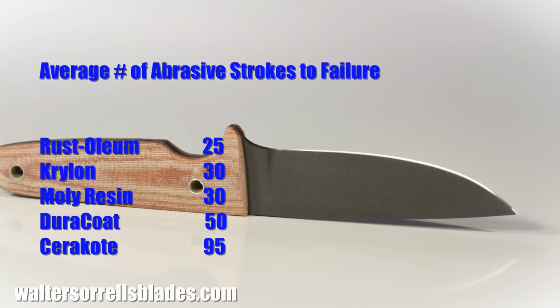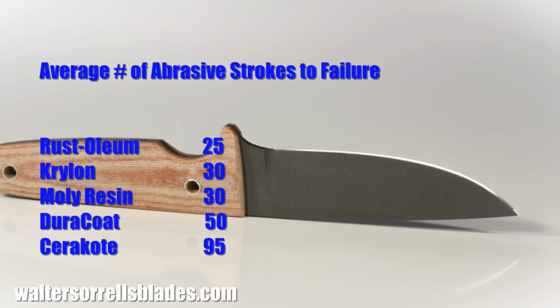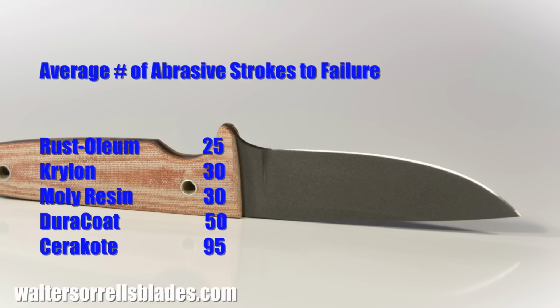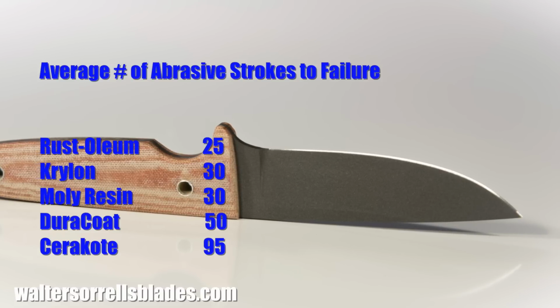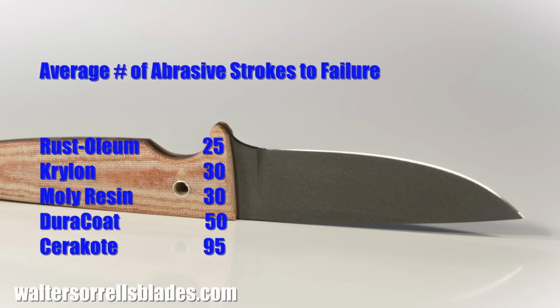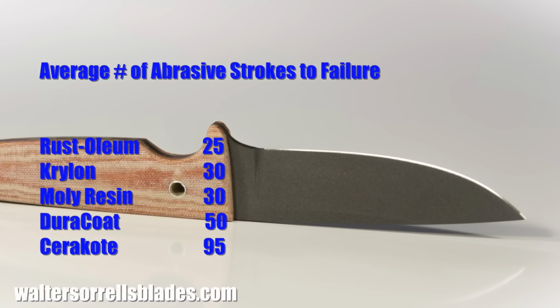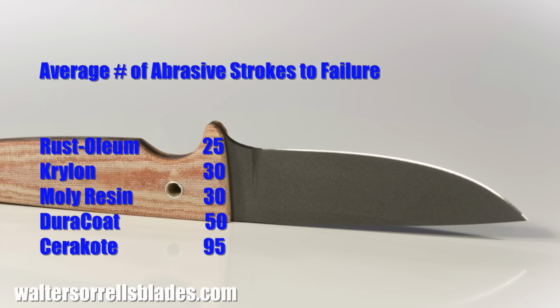DuraCoat was next, averaging 50 strokes before it gave up the ghost. And at the top was Cerakote with 95 strokes on average before it crapped out. Also, subjectively, Cerakote just felt the most robust. But that said, at the end of the day, all of these wore out fairly quickly. A little more so than I expected. All the samples from top to bottom were showing some bare metal about 30% of the way before I quit.